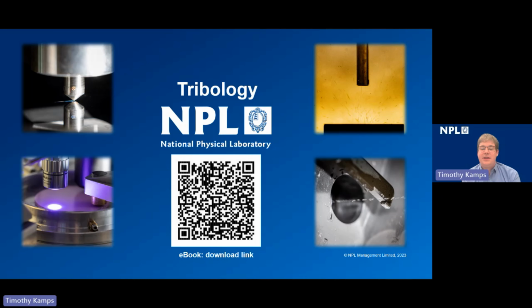The high temperature capability also has in situ mass loss, and this allows for high throughput, high temperature testing, as conventional solid particle erosion done at elevated temperature requires the samples to be cooled down in between each weighing interval. Whereas having the system in situ allows us to keep the sample and test rig at temperature and make the measurement, which offers a considerable time saving. Again, part of that approach of offering high value testing at NPL.